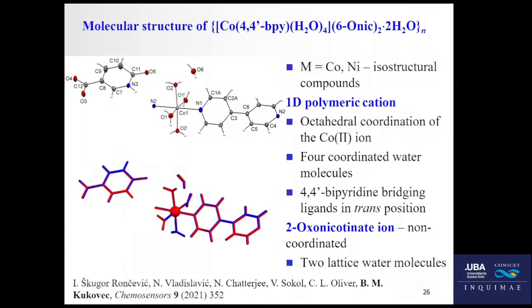Regarding this coordination polymer, the cation is the same as I mentioned previously. It is the cobalt coordinated with bipyridine ligands and 4 water molecules, and the anion is just the hydroxynicotinate anion, which is not bound to any metal. So it's not coordinated, and we also have some lattice water molecules here.